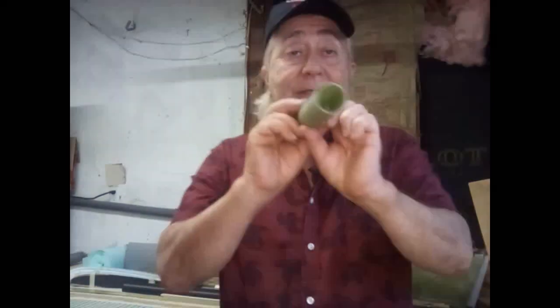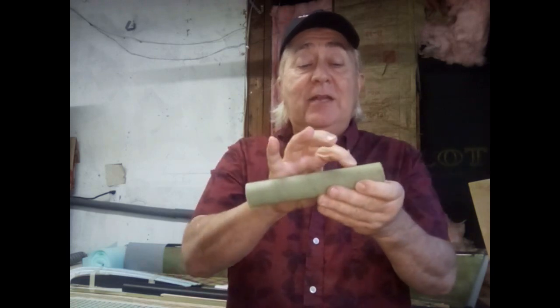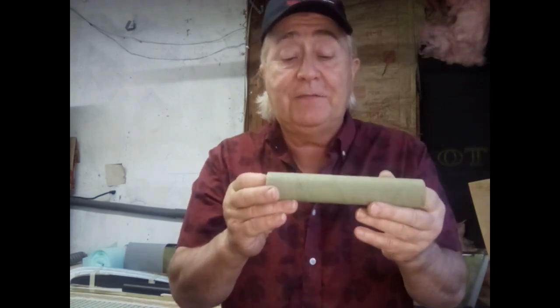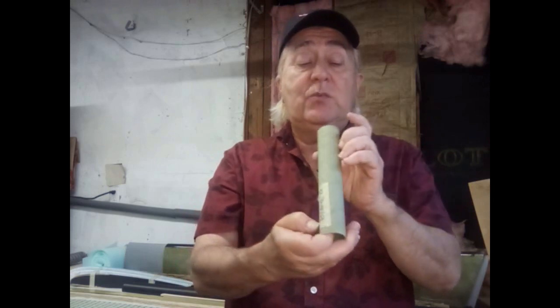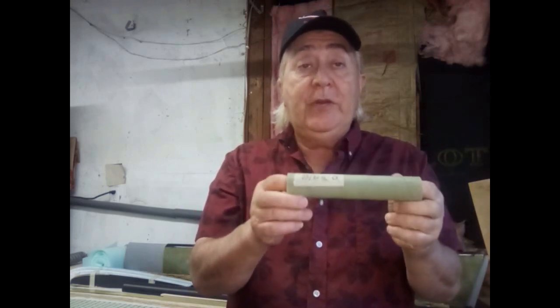And it comes out like this. Here's a piece of it. This is 1/16 Airex foam. And on the inside is one layer of 3-ounce fiberglass. And on the outside is one layer of 1.5-ounce fiberglass. And this slightly over 1-inch diameter tubing only weighs 3/4 of an ounce per foot. And it's phenomenally strong. This is only a little bit heavier than the carbon fiber tubing that I collapsed into nothingness.